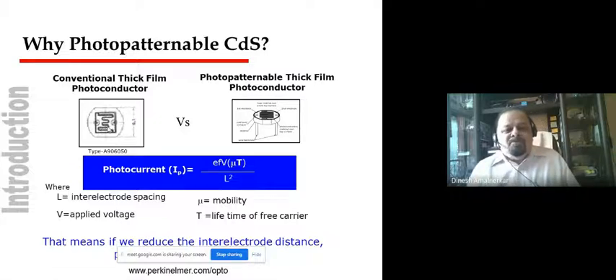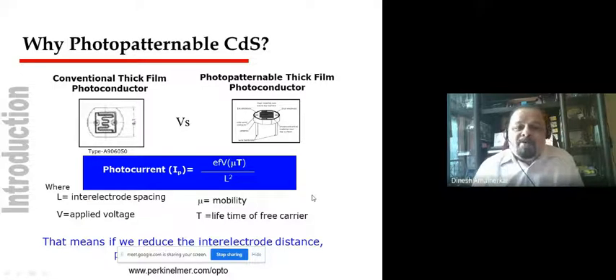So we thought, why not use a photopatterning technique and try to have an interelectrode distance of the order of 100 microns in comparison to half a millimeter, so that, because of this inverse proportionality to L square, we can get the maximum photocurrent. This means if we are successful in reducing interelectrode distance, probably you can make a highly photosensitive micro photosensor. And this we call the micro photosensor. With this 100 micron line at interelectrode distance, it is definitely a micro photosensor. That's why we call it a micro photosensor.